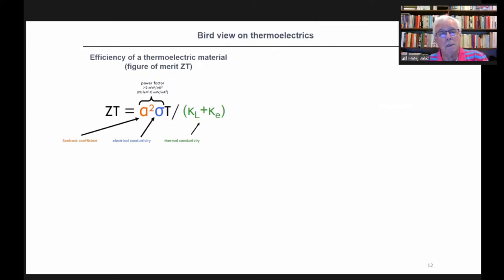The last picture in this set of figures is a bird's-eye view of thermoelectrics. Of course, we need to look at the efficiency of thermoelectric materials. We use a parameter called the figure of merit, ZT, and this describes the quality of a material. The first paper on this parameter and this formula was published by Abram Joffe in 1957. If you look on the first side here, if you need high ZT, both the Seebeck coefficient and electrical conductivity must be large, while thermal conductivity, this green color, must be low.